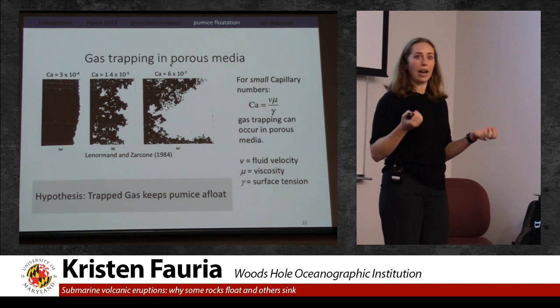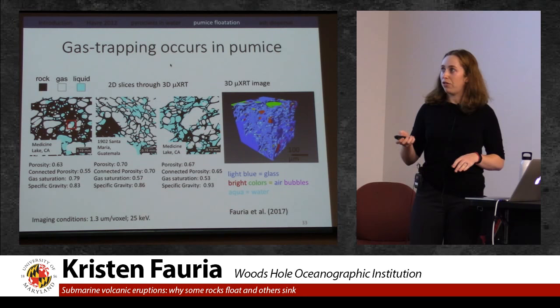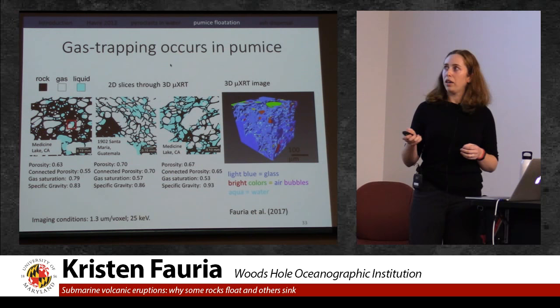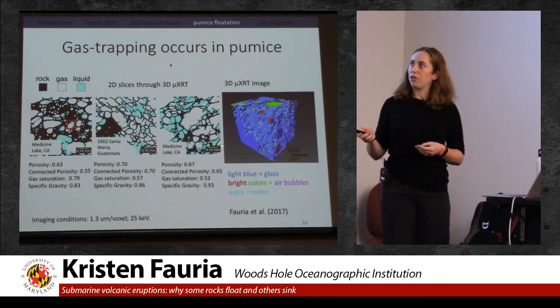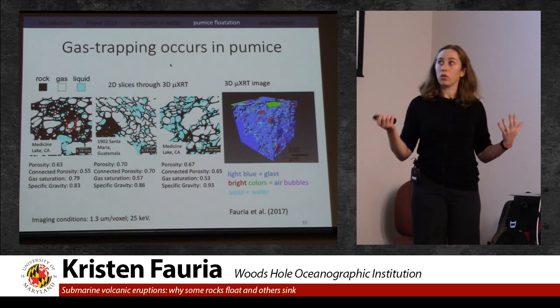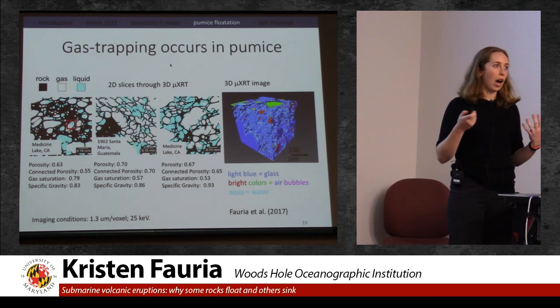And so here's what we found. These are 2D slices through our pumice. The black is the rock, the white is the gas, and the blue is the liquid water. We find that there's liquid water in many cases surrounding the gas phase. It's not just the rock that's enclosing the gas inside. And we find this for both hot and ambient temperature pieces of pumice.